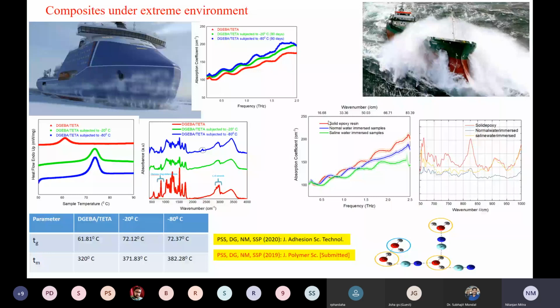Obviously, we were doing a lot of different things, like differential scanning calorimetry, IR spectroscopy, terahertz spectroscopy, and looking into the molecular aspect of how the molecule changes over time once you subject it to a significant amount of temperature conditions. In this case, we were testing it at -20 and -80 degrees centigrade for a long period of time, around 2 to 3 months.